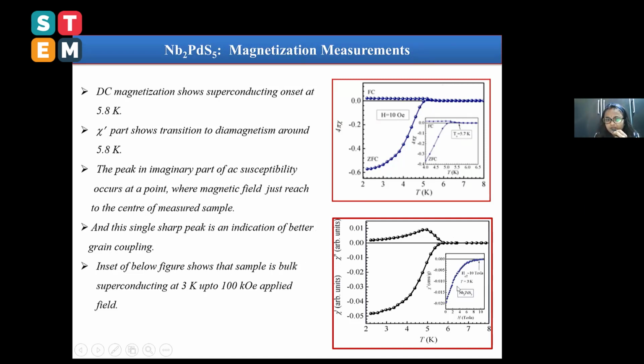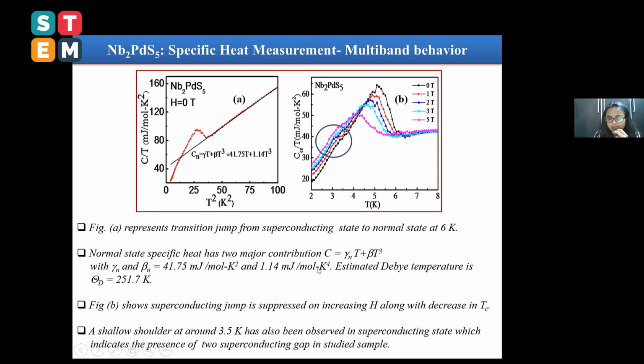In the inset of this figure, you can see that at T equal to 3 Kelvin, when we increase the magnetic field from 0 to 10 Tesla, the real part is still negative. That is, it shows superconductivity, which is another confirmation of the robust behavior of superconductivity against magnetic field.